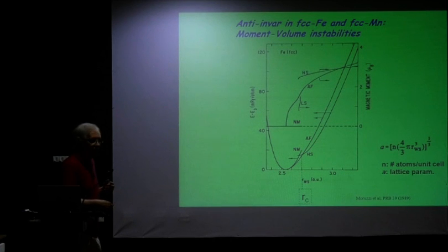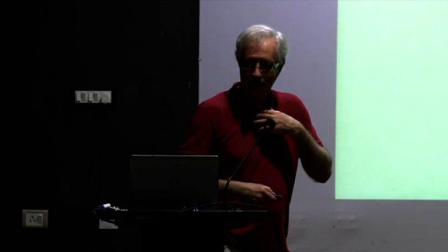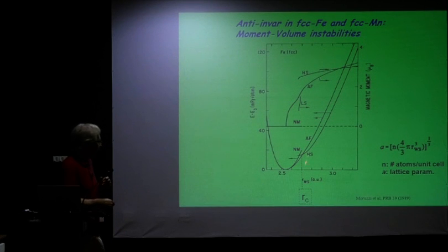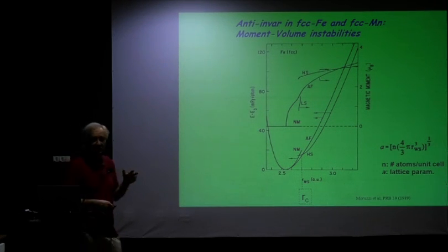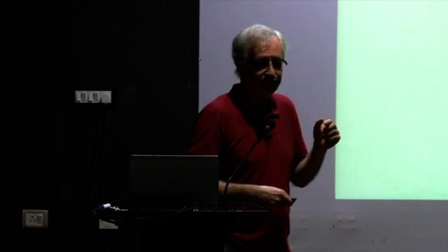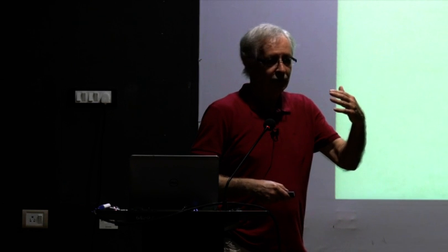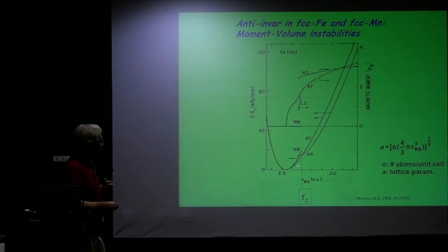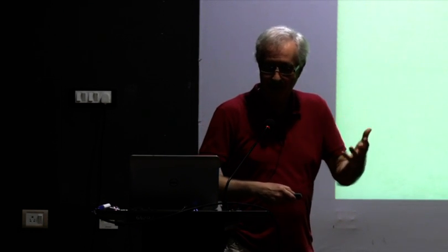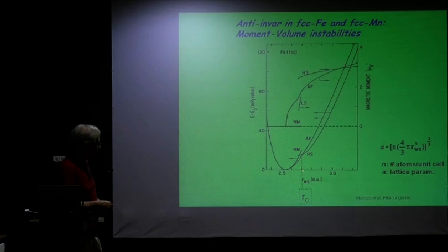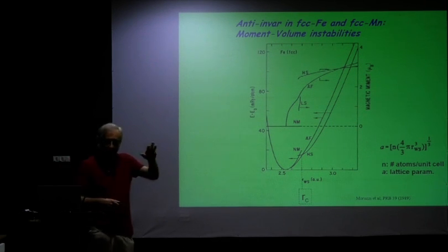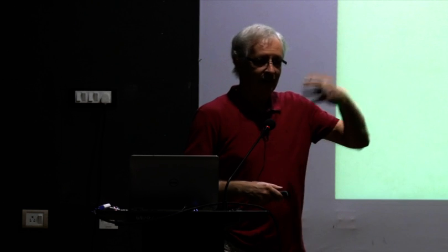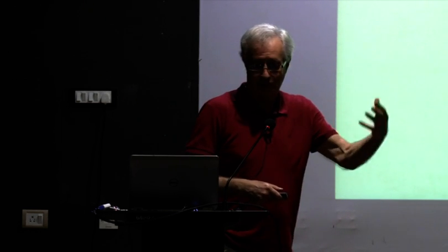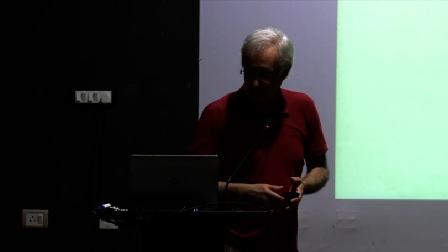And 1 millielectron volt is 11 Kelvin. So in the case of FCC iron, it's in the order of about 10 millielectron volts, in hundreds of kelvins. So what happens is that by thermally heating, it is possible to actually go from an antiferromagnetic decoupled state, or a low spin state, to a high spin state within the thermal range. In the case of manganese,